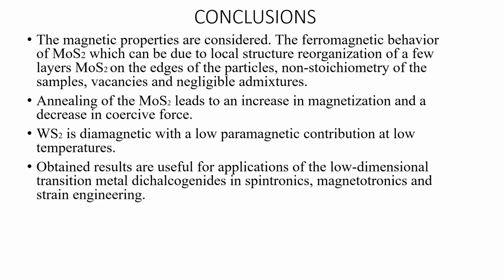Conclusion. In our work, the magnetic properties were studied, comparing experimental results with models and theoretical calculations. The manifestation of the ferromagnetic properties of molybdenum disulfide could be explained by the local structural organization of a few layers of molybdenum disulfide on the edges of the particles, non-stoichiometry of the samples, vacancies and negligible admixtures. Annealing of the molybdenum disulfide leads to an increase of magnetization and a decrease of coercive force.